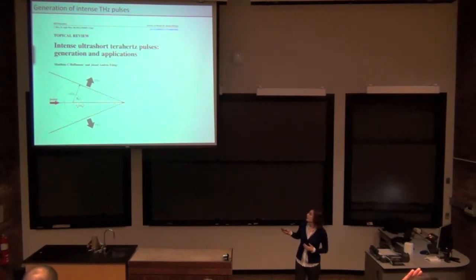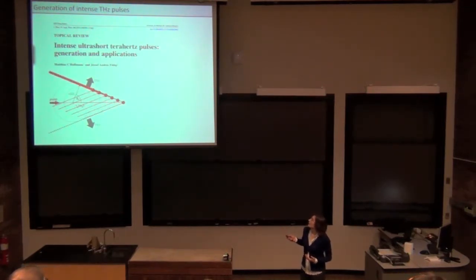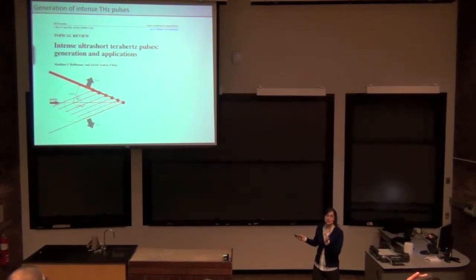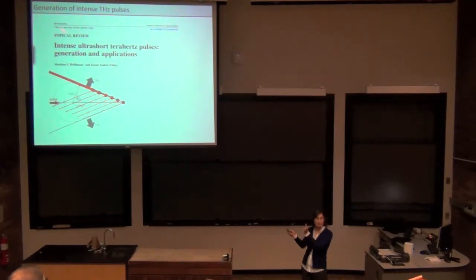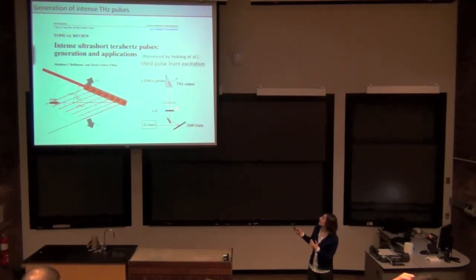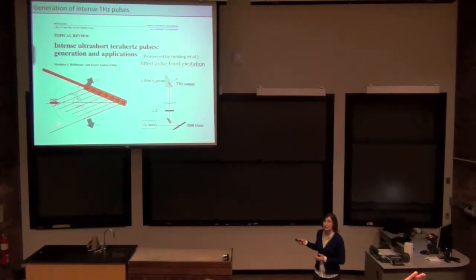If we tilt the pulse front by exactly this angle, about 63 degrees, then their optical excitation beam is tilted like that, and in the terahertz generation direction they now propagate together. All their generated terahertz waves interfere constructively, and we have this plane wave of terahertz being emitted in this direction. For that to happen, we need to take this lithium niobate crystal and cut it to exactly 63 degrees to get this sort of phase matching configuration.